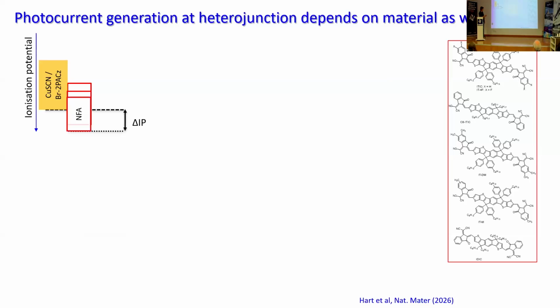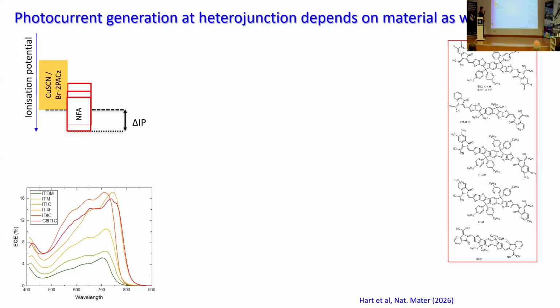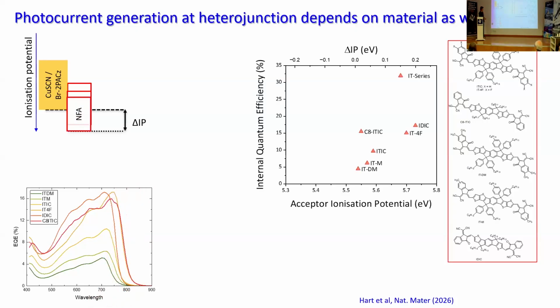As part of this, we looked at photocurrent generation at heterojunctions between our acceptors, which we call NFAs, non-fullerene acceptors, with different ionization potentials that present a different offset next to this copper thiocyanate donor layer. We look at the quantum efficiency, and not surprisingly, as we make that offset larger, the quantum efficiency gets better. We can plot that. This is exactly what we've seen before, that as this offset gets larger, photocurrent gets larger until it saturates.